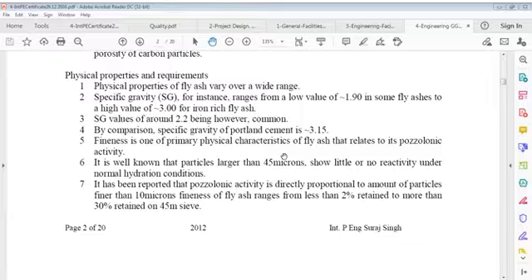Fineness is one of the primary physical characteristics of fly ash that relates to its pozzolanic activity. It's well known that particles larger than 45 microns show little or no reactivity under normal hydration conditions. It's been reported that pozzolanic activity is directly proportional to the amount of particles finer than 10 microns. Fineness of fly ash ranges from less than 2% retained to more than 30% retained on a 45 micron sieve.